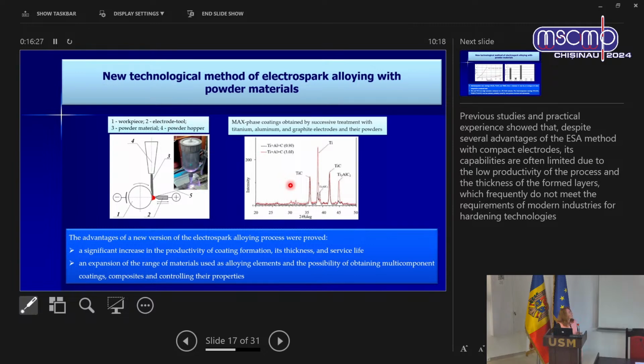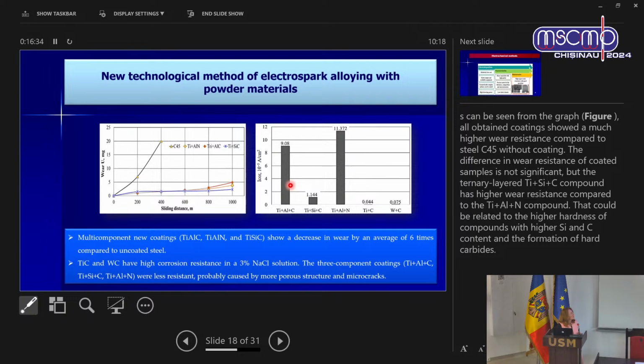And here, briefly, I represent that, okay, for example, this is a substrate. And this material is new, obtained by this new method, and you can see that, of course, their resistance is much better. But, however, in comparison with bimetallic systems, the corrosion of these coatings still needs to be improved, which our laboratory is improving now. Working on this because nevertheless the wear resistance is very nice, but they are mostly porous, and we are working on stabilizing the regimes of these coatings and to make a better, more improved coating.